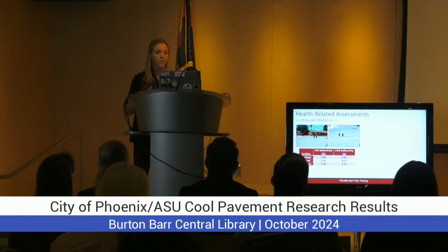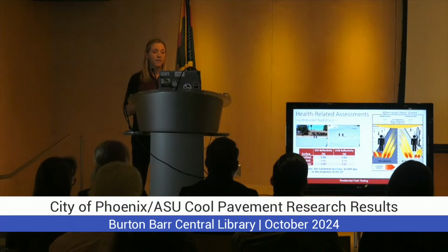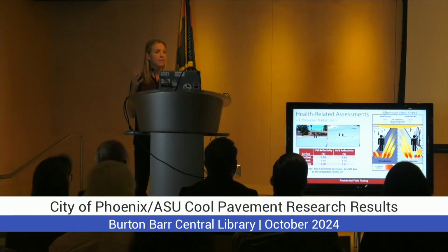And that's a very promising result, so that we're able to say, no, it's not going to increase your risk of burning your skin, largely because the way the cool seal product works is it has titanium dioxide in it that absorbs those UV radiation rays instead of reflects them like some surfaces do. So that's great. And then we did do a test of afternoon heat stress, just because of that higher radiant load on a person if they're standing in the middle of the road.